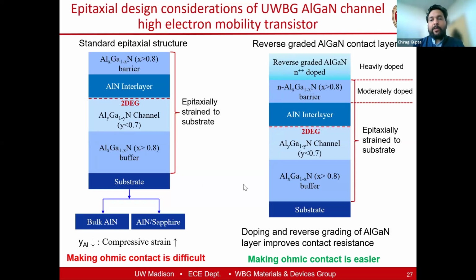And still there is a lot of effort that is being put on this to lower the contact resistance. Still the contact resistance is extremely high and non-trivial to make ohmic contacts, and it requires a bit of material and device engineering both to give you low resistance ohmic contacts. So recently we have gotten reasonably low contact resistance, somewhere close to 2 ohm millimeter with these. So that work is under review at the moment. So hopefully that will be available soon.